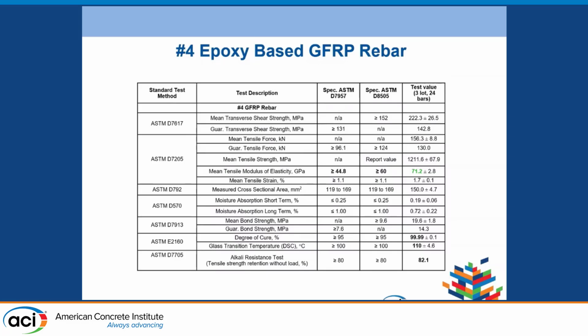Similarly for the number 4 bar, the tensile strength is about 1,000 megapascal. Here the data is about 1,200. And the tensile modulus is also about 70 gigapascal. The degree of cure is near 100%, Tg is 110. So it meets all the ASTM D7957 and ASTM D8505 requirements.